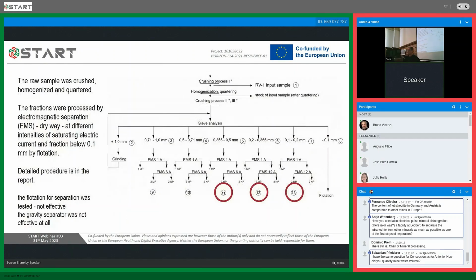The raw sample, what we sampled in the mine, was crushed, homogenized, and quartered. This is a scheme, and here the circled samples were the provided samples of concentrates. The fractions were processed by electromagnetic separation in a dry way at different intensities of saturating electric current, and the fraction below 0.1 millimeter by flotation. The detailed procedure is in the report. It's on the SharePoint, in work package 2, if somebody would like to look for it.